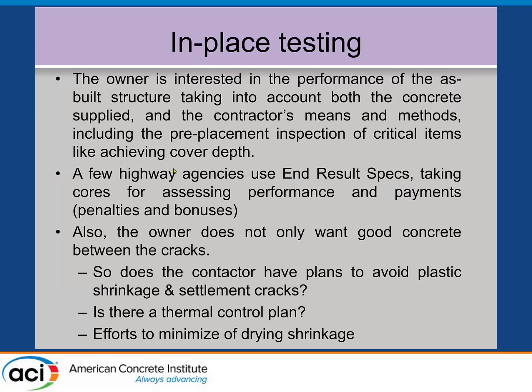A number of agencies, like our Highway Department in Ontario, have been using end result specs for the last 20 years, and they assess performance and make payments, penalties, and bonuses based on whether statistically based core results meet the requirements for strength, for air, for rapid chloride permeability. And they also want to look at what's the in-place control, and this is where 301 has thermal control plans, controls on shrinkage. What do you do if there's shrinkage and cracking? What are you doing to prevent cracking?